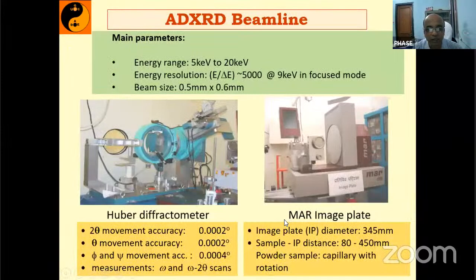And these are just for completeness, the XRD beamline. Here one can do X-ray diffraction between 5 keV and 20 keV. Normally in our laboratory, we are using the copper K alpha, that is 8 keV. But here you can have the energy variation as well as pressure variation and temperature variation. So temperature dependent X-ray diffraction and pressure dependent X-ray diffraction, that kind of thing one can do at this X-ray beamline.